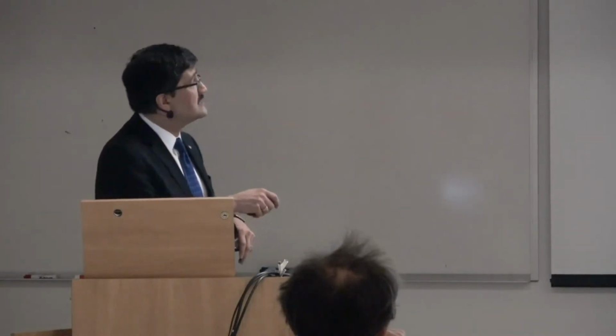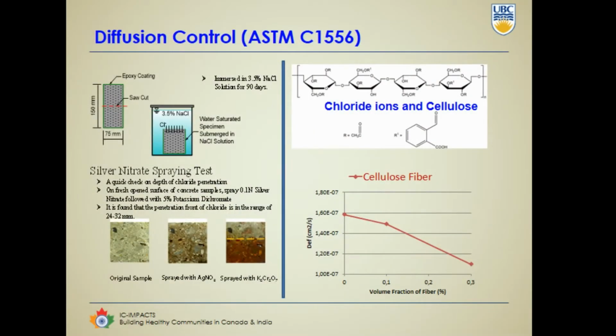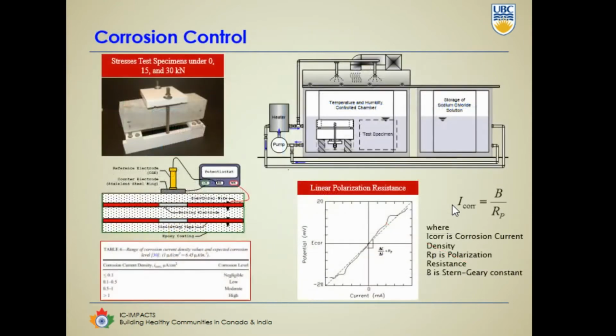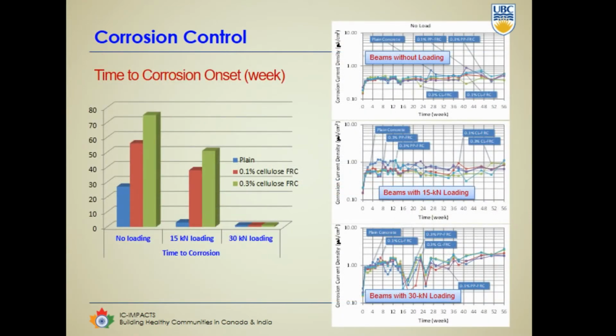So if you look at these systems, with our cellulose, we ran some tests here. Here's the loaded beam, which is in a highly aggressive, highly corrosive, highly chloride-laden environment. So we are causing this particular rebar to corrode, and we are monitoring the corrosion activity through a number of methods, linear polarization, half cell, and those kinds of things. And what we notice, which is really the proof of the pudding, as I call it, is the time to corrosion in terms of weeks. And of course, these are accelerated tests.